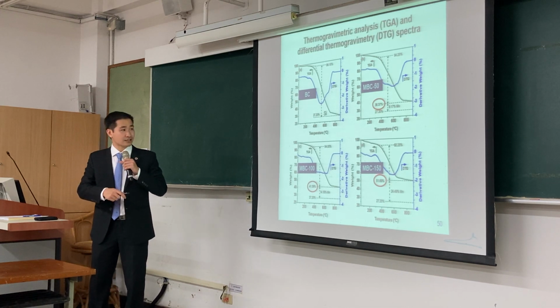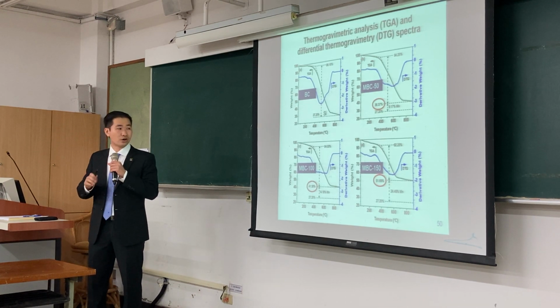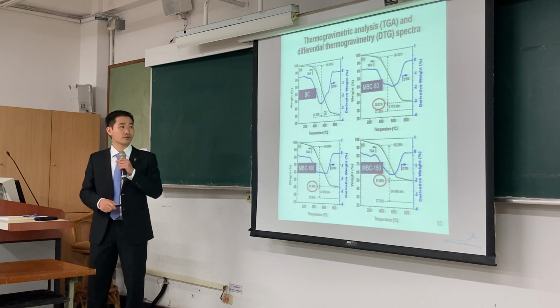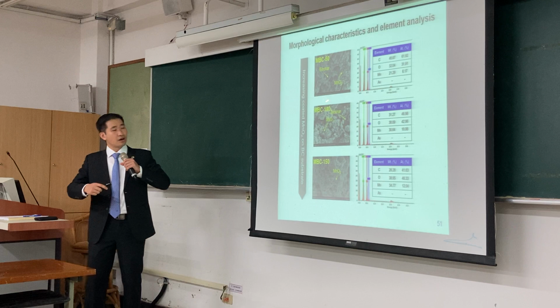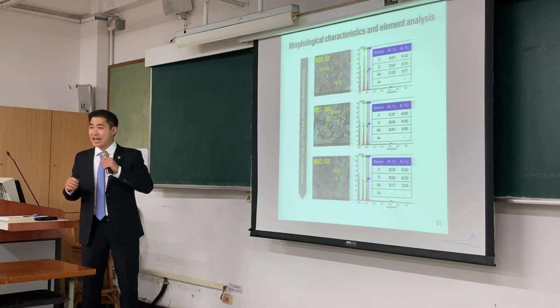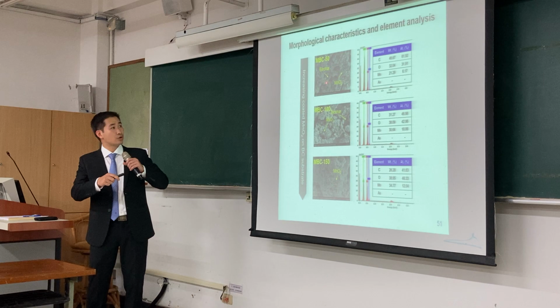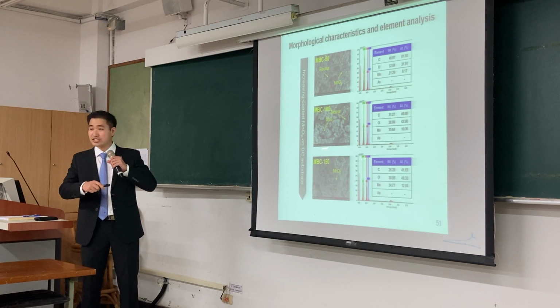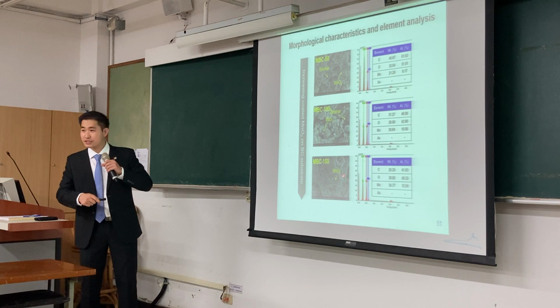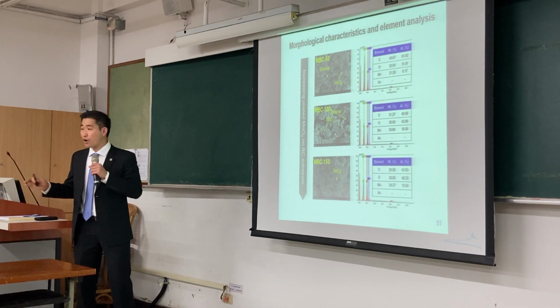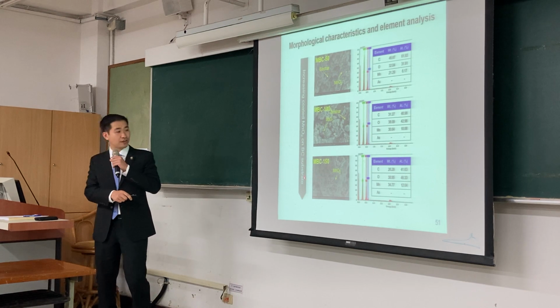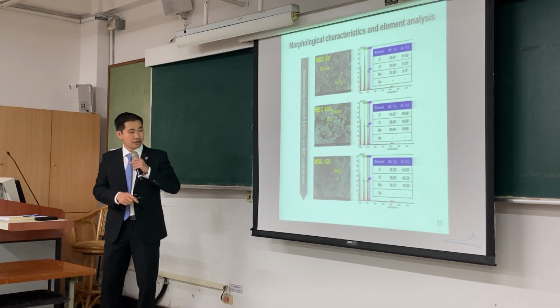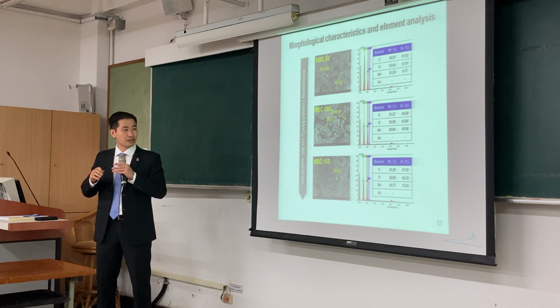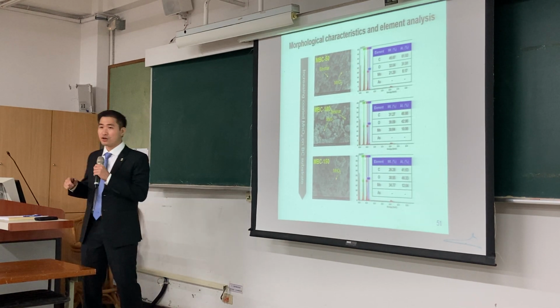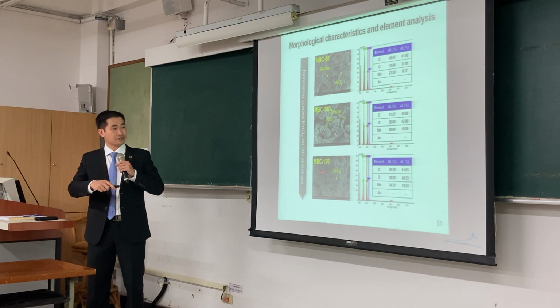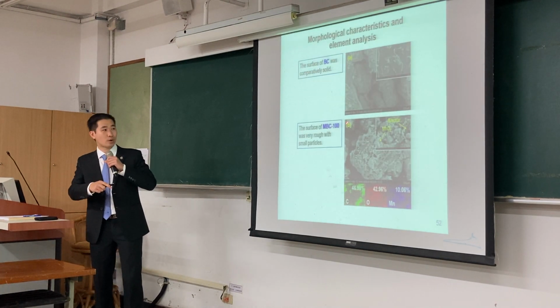It indicates that the mass of manganese dioxide on the biochar is well controlled. Obviously, we can see the area of manganese dioxide particles on the biochar substrate is larger when the reactant concentration increases. However, it seems that MBC-150 is completely covered by manganese dioxide particles. Therefore, for future investigation, I focus on the comparison between MBC-100 and BC.